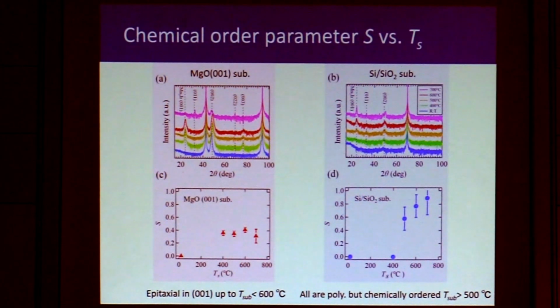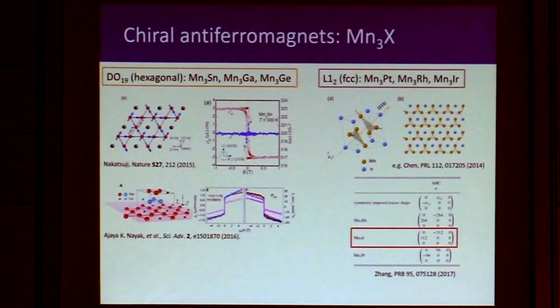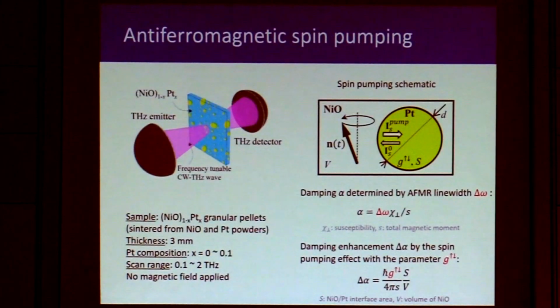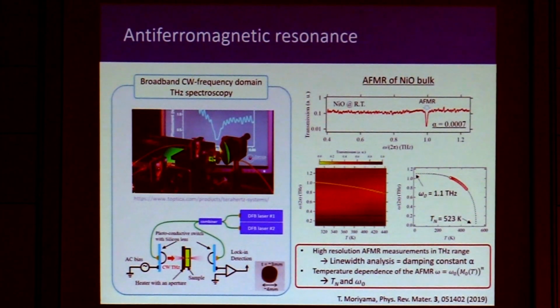Can you go back to the nickel oxide, the temperature dependence of the resonance? Indeed you have a very good variation of frequency from 1 terahertz to 0.8. As you increase temperature, frequency goes down. So think about it. If you look at the width for a particular platinum composition, you expect dynamical damping to increase with frequency, but when you increase temperature, you actually decrease the frequency. So if you look at the evolution of your width as a function of temperature, you will be able to tell whether this is combined.